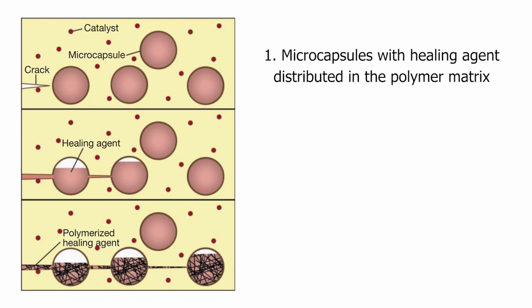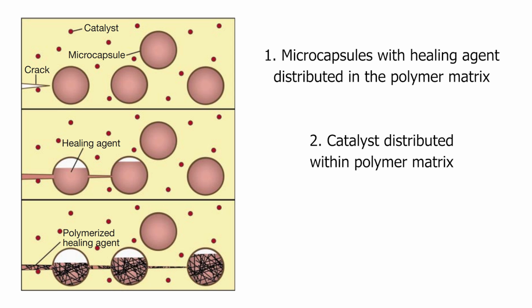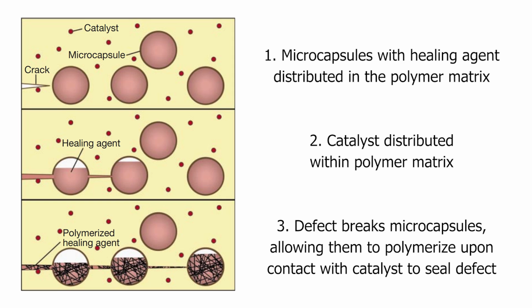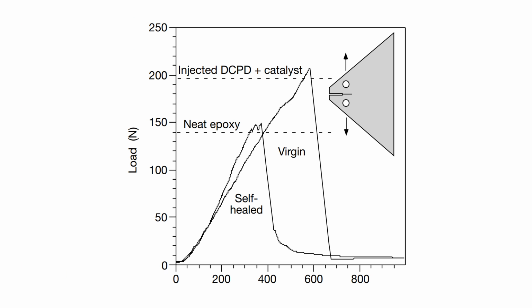Microcapsules containing a healing agent, dicyclopentadiene, were immobilized within the polymer material. The polymer itself contained a catalyst that would react with the healing agent upon exposure. When a crack traveled through the material, it would break the microcapsules and release the healing agent, which would polymerize upon contact with the catalyst to create a network that would effectively stop the growth of the crack and fill in the defect. This method required no external intervention and could restore 75% of the maximum load of the material.